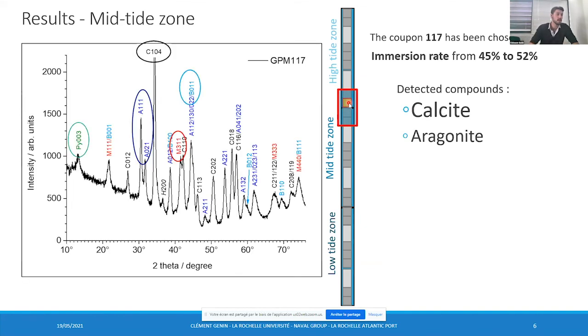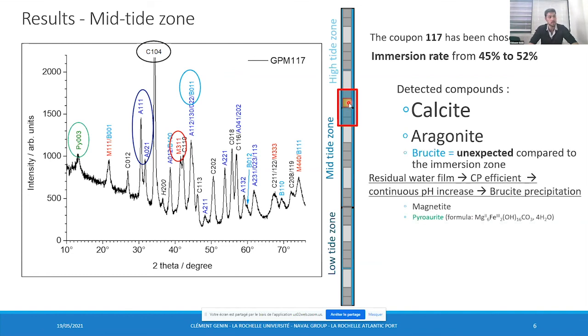Higher in the tidal zone, in the mid-tidal zone, this coupon is presented, representative of this area, with an immersion rate of 45 to 52%. The obtained diffractogram is presented here, with still a lot of calcite which comes from the shells. Aragonite is present too, as an indicator of the cathodic protection, and brucite is detected too, which was really unexpected. As I said before, brucite requires a high interfacial pH to precipitate and really low cathodic potentials. Indeed, with the galvanic anode, it's rarely achieved.